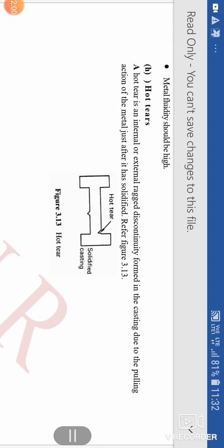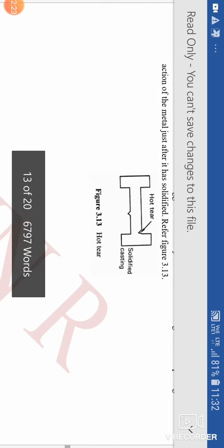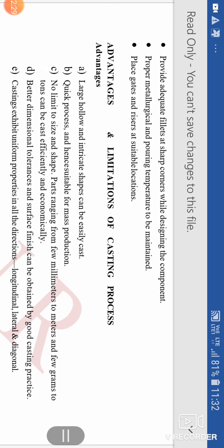Hot tears. Next one, hot tears. A hot tear is an internal or external ragged discontinuity formed in the casting due to the pulling action of metal just after it solidifies. So you can see a hot tear here in the figure. Remedies: provide adequate fillets at sharp corners while designing the component. Proper metallurgical and pouring temperature to be maintained. Place gates and risers at suitable locations.